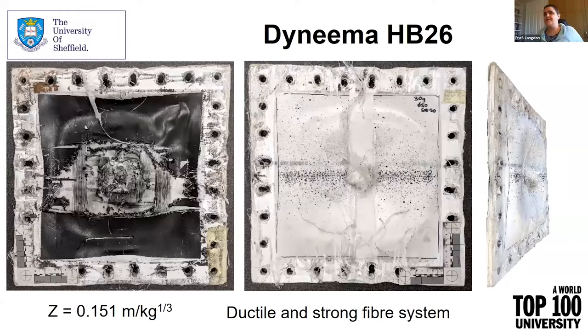So on the front face, which is the far left image that you can see, it's been blackened, because what we found when we first started testing Dyneema is that if you don't blacken out that face, the blast transmits a lot of light through the composite material, making it very difficult to pick up the speckle pattern on the back side, so you couldn't do such good transient response measurements. So that's why the front surface is completely black. So the area in the center that isn't completely black, that is sort of more whitish, is the original area of the Dyneema, like you can see around the clamp frame. So effectively what's happened there is the black paint has come off or been burnt off. I can't tell you which at this point, probably a combination of them both.